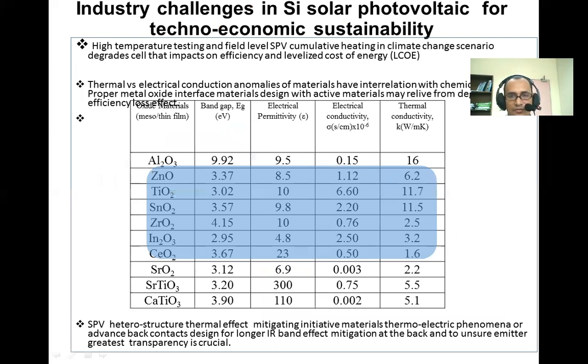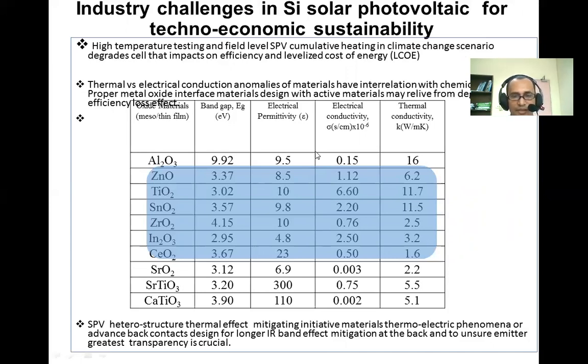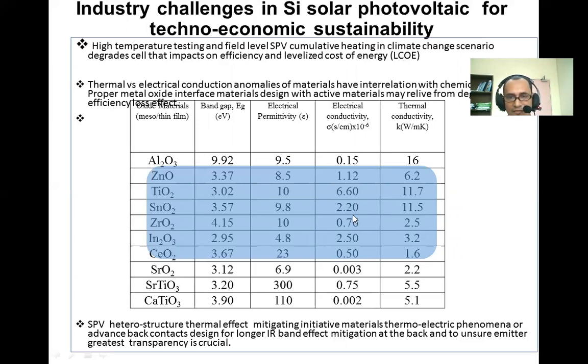Another core aspect to discuss in solar photovoltaic advancement is electrical permittivity, because binding energy is the core issue related to electrical permittivity. Materials with higher electrical permittivity have lower binding energy, which supports minimizing the energy required to extract electrons or holes from the system. That is why high electrical permittivity, higher bandgap materials are preferred as emitter interface contacts. Additionally, infrared range absorption is predominant at the back-end contact, so not only electrical conductivity but also thermal conductivity must be considered when designing interlayers for better optoelectronic energy transformation.